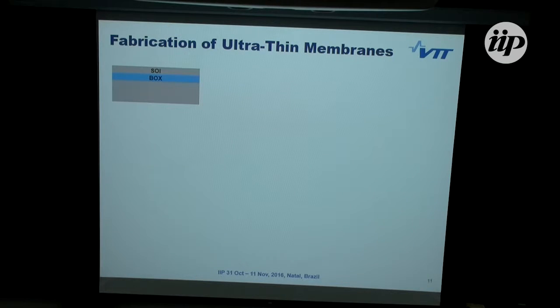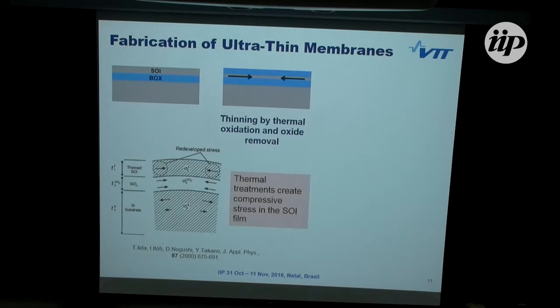So how to make the membranes then? We have this starting wafer, and then we start to oxidize the silicon layer on top. This oxidation is very well controlled, and it forms extremely good interfaces, and the control of thickness is down to one nanometer, and also one can go down to, let's say, 2 or 3 nanometer thick silicon layers. Then this oxide is removed, but now the problem is that these thermal processes create compressive stress in the SOI film.